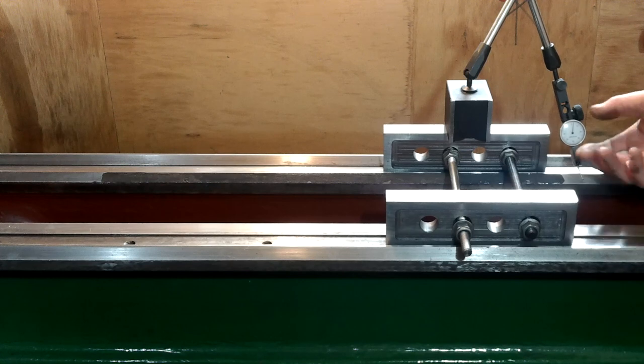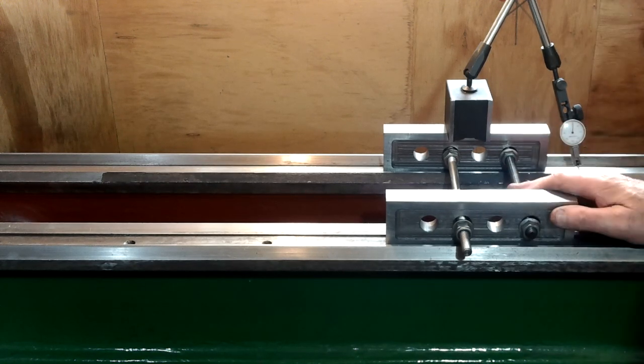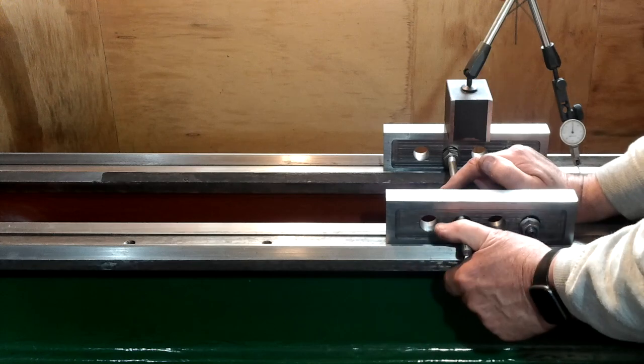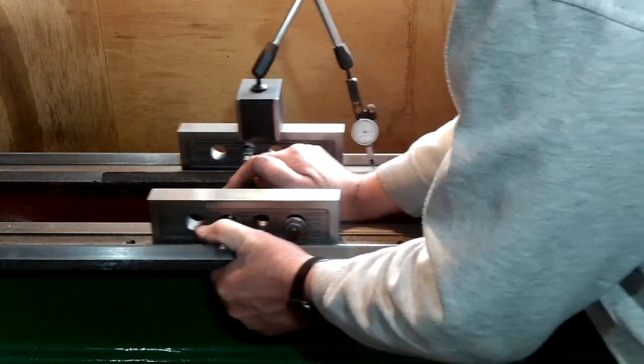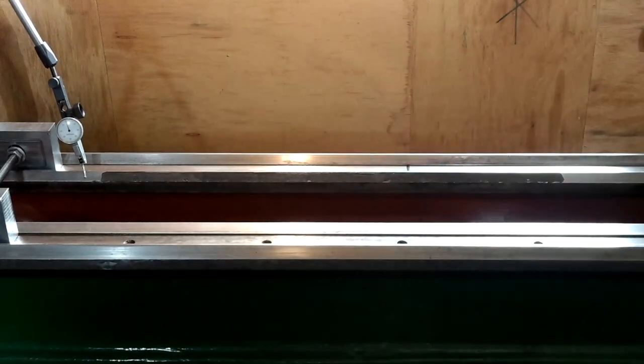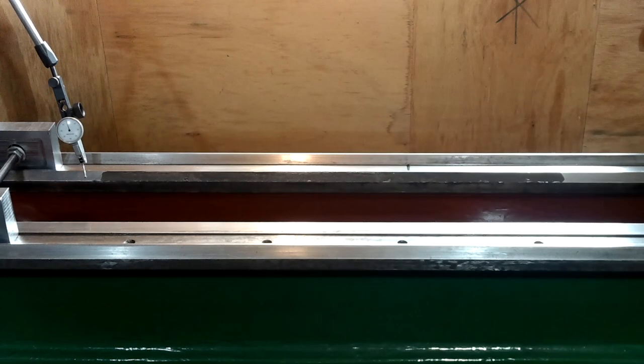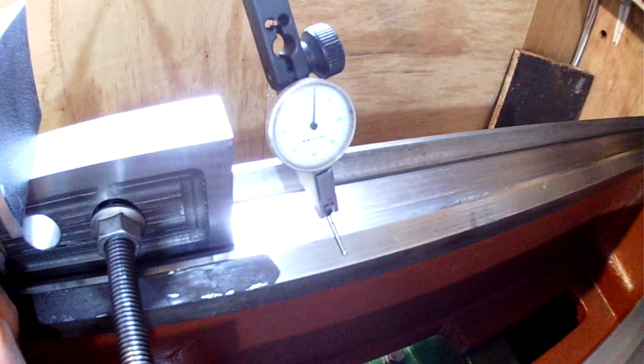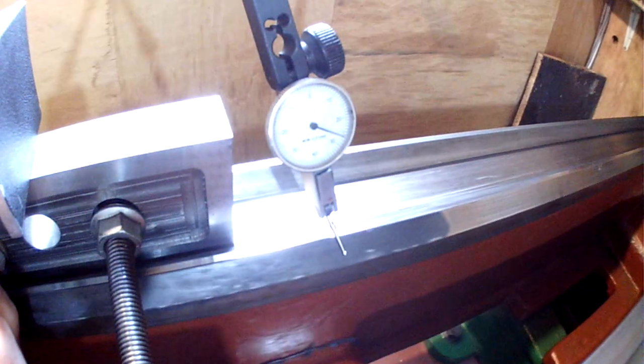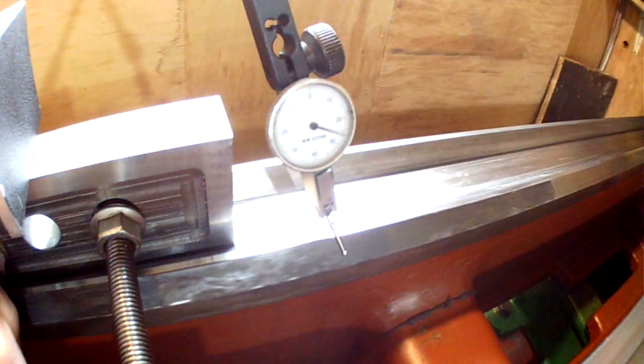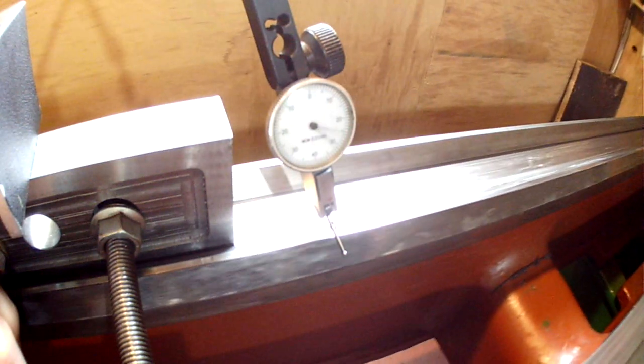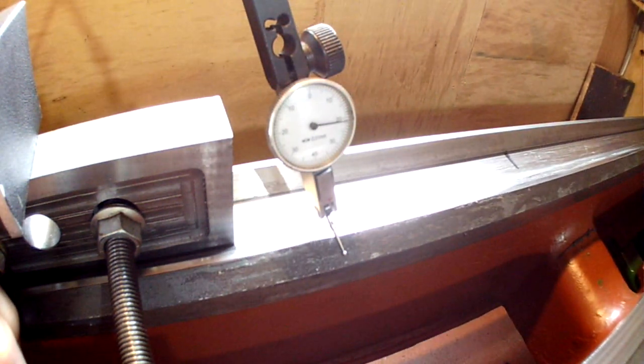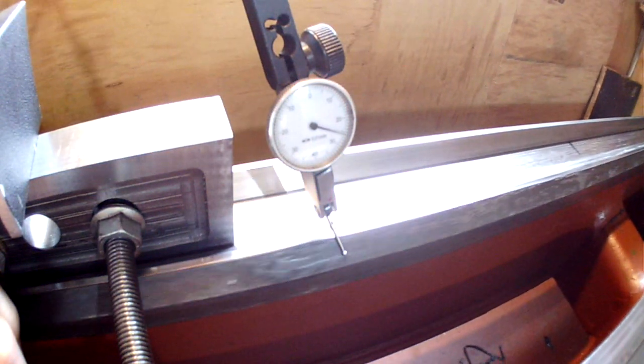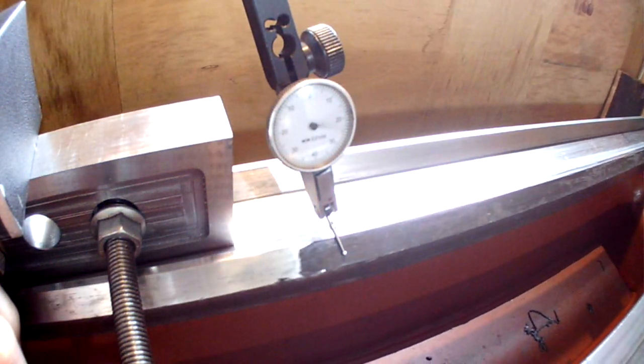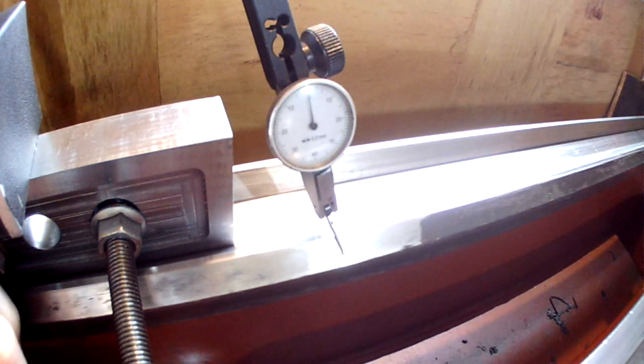The first thing I did was to use a craft knife to trim off all of the excess resin and clean off any flashing. This was a particularly easy task because the resin, although set, wasn't rock hard. It was a bit like soft rubber. Shaving the excess resin off the important surfaces at this moment in time was a good call, because after a good 24 hours it really was set, and the resin had built up to about 0.2 to 0.3 millimetres, that's about 8 to 12 thou above, and that's good.